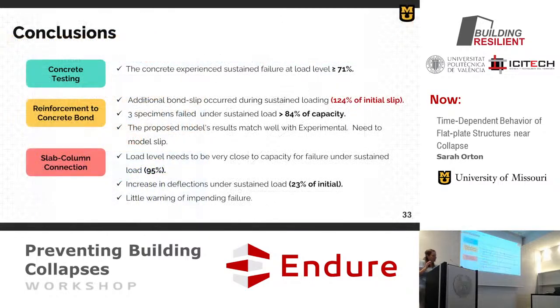And so what I learned in this test is, concrete itself, the material that we had, experienced failure at about 70%. Concrete is susceptible to creep deformations and failure. When I look at the bond, I had about 84% of the capacity, and I had a lot of slip as well, a lot of slip in that bond. And so when I did my models, I needed to apply that bond slip model. That worked out a lot better.